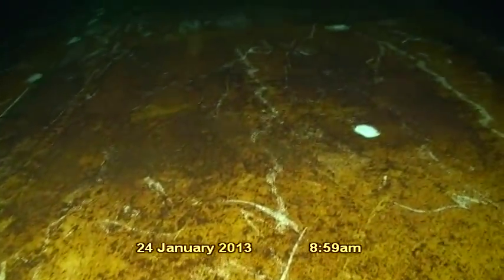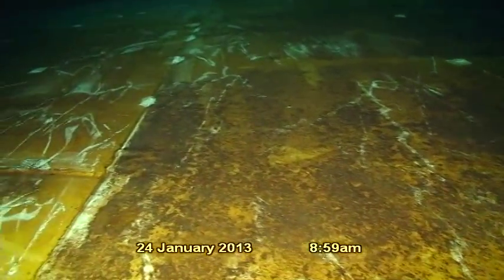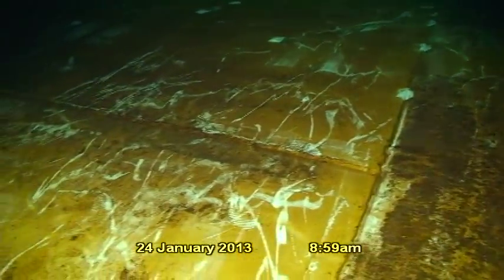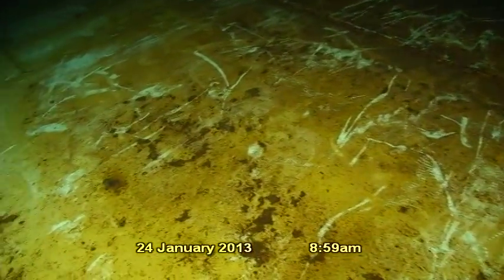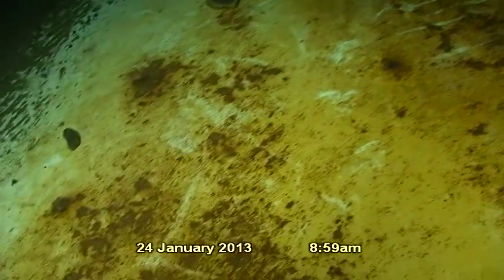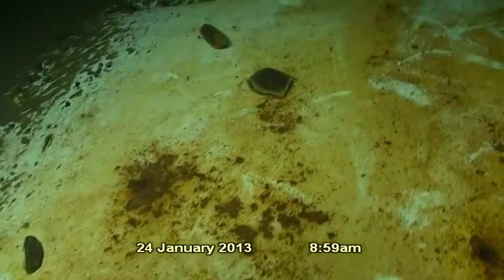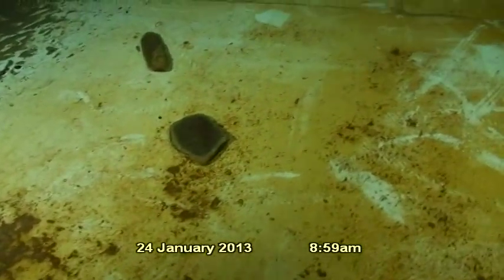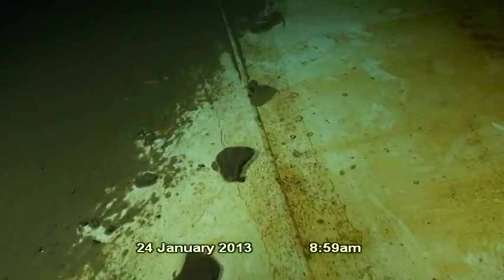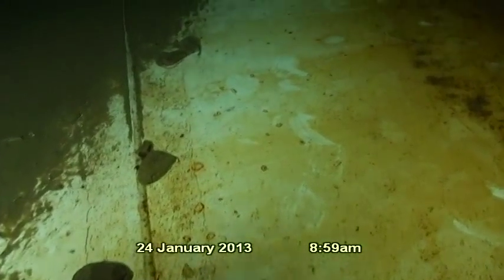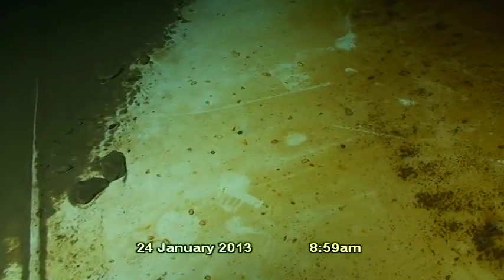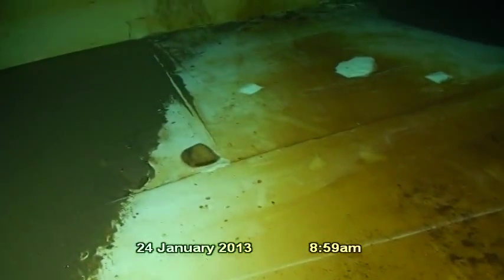Aquatic Inspections would recommend that consideration be given to recoating the interior of the facility. In many areas on the floor, the lowest 20 feet of the shell and the lowest 20 feet of the center pole, the coating is losing flexibility, cracking, and delaminating, resulting in light surface corrosion. Additional large pieces of concrete chips are present on the floor and being removed by the two-man dive team. All of the loose sediment and debris was removed from the interior of the facility at the conclusion of the wet inspection.